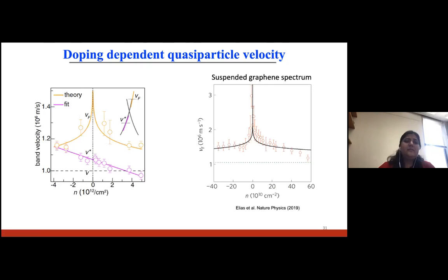Moreover, when you have alpha approaching 0, which is this fully screened limit, we get this non-interacting velocity, which is shown here by this horizontal line. And for the band velocity, which is the star, we find that there's a continuous decrease of the velocity as the Dirac cones are shifted to higher binding energy with increasing electron doping. This is due to electron-hole pair scattering processes at a higher binding energy, so this is expected.